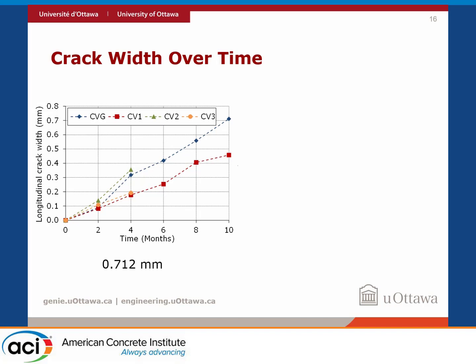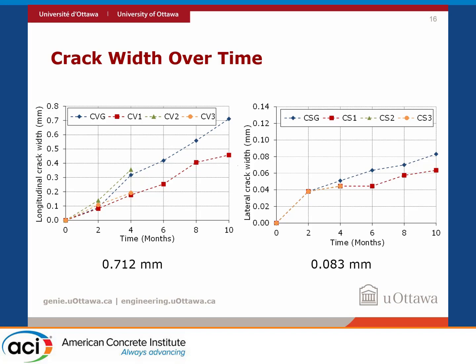When we look at the other specimens, where only the spiral reinforcement was corroded, if we look at the magnitude of the crack width first, we can see that it's much smaller. So longitudinal cracking was 6 to 8 times greater in the CV specimens than the CS specimens, even though we are going to see later on that the mass loss was similar. So we believe that this is one of the effects of sustained loading, because the CS specimens experienced cracking that was perpendicular to the load. So the load actually helped keep those cracks smaller.